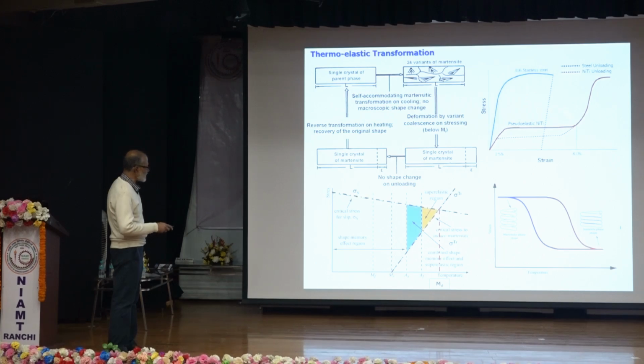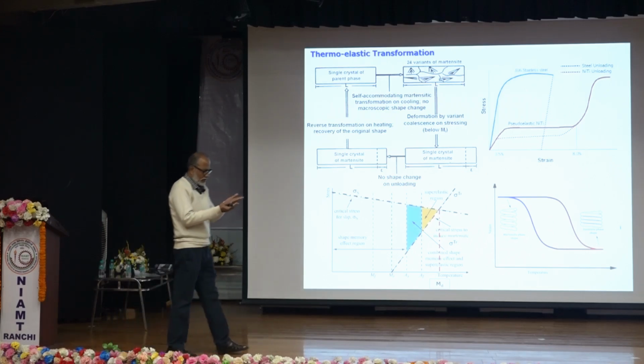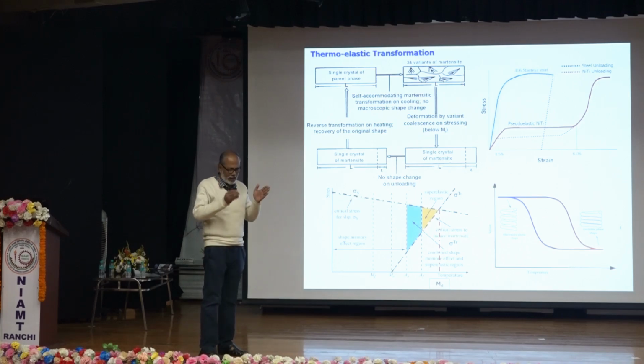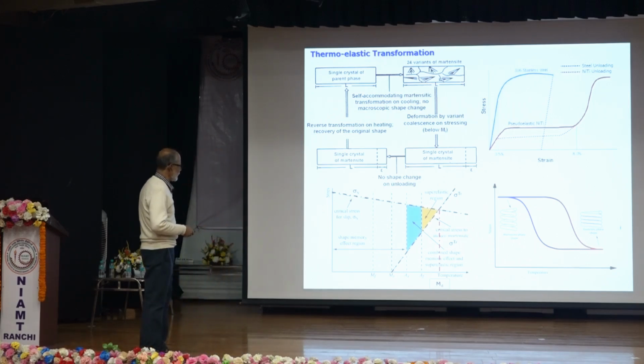So as I have mentioned, as this is recoverable, it occurs below the yield strength, right? And when the transformation occurs below austenite start temperature, we call it shape memory effect, shape memory region. And when it occurs above the austenite start temperature, even in austenite, suppose you have austenite, you apply a certain strain and remove it. I compress it. When I withdraw the strain, it gets back to its original shape. So that we call superelastic behavior. And this occurs above austenite start temperature in the austenitic region. And in between there can be an overlap.